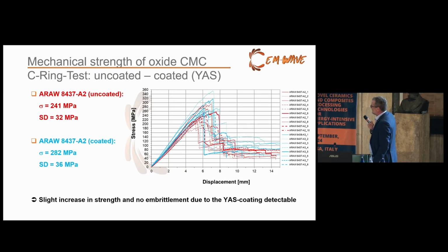Here, in the case of the oxide system, we could show in the C-ring test, where we cut the tube into 10 millimeter slices, then slice the ring open to a C-ring, and apply pressure on it and look at the residual strength which we get. And here you see that we have a nice damage tolerant behavior of the aluminum oxide fibers, not in all of these curves, but most of them. And you see that we even get a slight increase in strength when we coat this aluminum oxide system with the YAS.